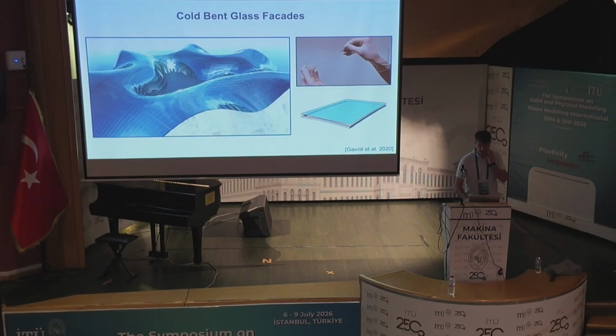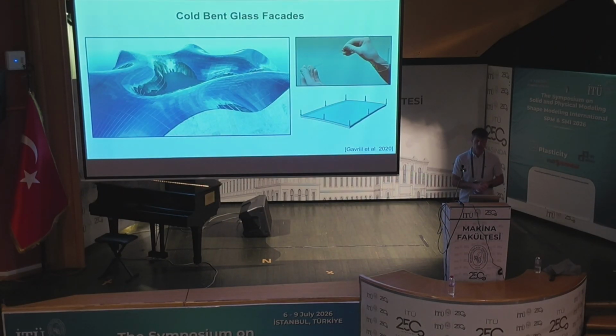So the idea is starting with an initially flat glass panel. We can bend it elastically to a pre-manufactured curved frame. And this method is much cheaper than traditional hot bending of glass, where glass is heated up and brought into shape. Because there, you need to shape each panel individually, as usually, if you have such intriguing facades, none of the panels are exactly the same.